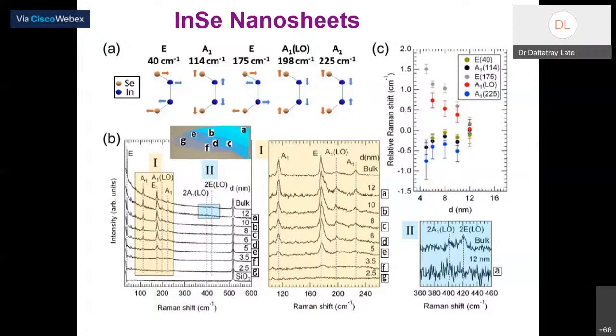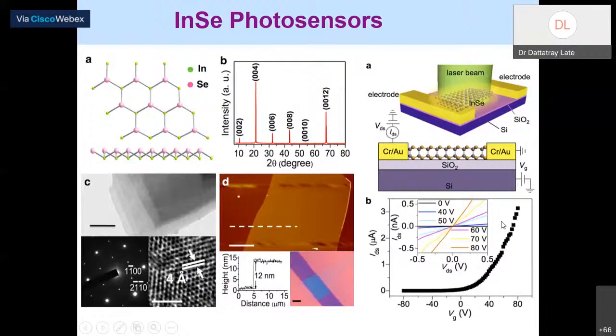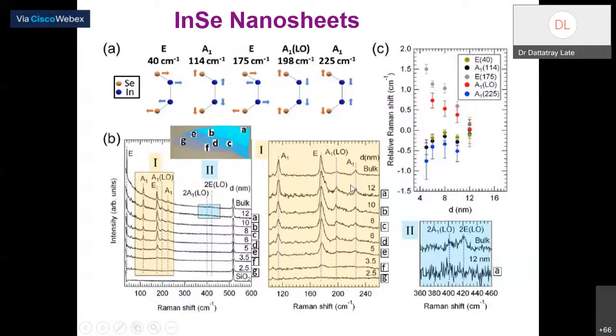See, when you do Raman spectroscopy as a function of various layers of indium selenide, you can see bulk here. In bulk Raman spectroscopy of indium selenide, you will be able to see this particular A1G mode, then A1 mode, right? This is for bulk, maybe more than say a 20 nanometer layer of indium selenide. You see this 12 nanometer, then you can see this 10 nanometer of indium selenide layer, 8, 6, and 5. You can see 3.5 nanometer.